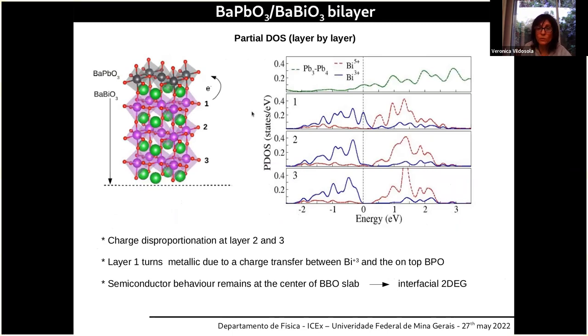From the electronic point of view, here you can see the projected densities of states layer by layer: layer 3, layer 2, layer 1, and the first layer of BPO. We observe here in blue the bismuth 3+ full state, and in red the bismuth 5+ empty state. Further away from the surface, we can observe the insulating behavior, and when we go to the interface, there is some hole doping of the bismuth 3+. The bismuth 5+ looks very similar to the one in bulk in terms of charge. And then there is some doping of the lead band, right? We have some electron doping from lead and hole doping in the bismuth 3+.